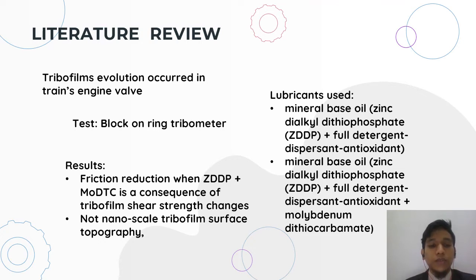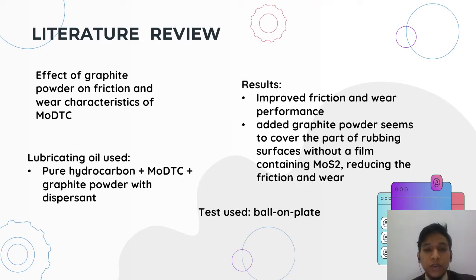topography of the tribofilm surface. The third literature review also presented a study about the graphite effect on friction and wear properties of molybdenum dithiocarbamate, MoDTC. It was found that graphite powder added with dispersant to oil consisting of MoDTC considerably improved friction and wear performance, while graphite powder appeared to be absorbed on rubbing surfaces but without a film consisting of MoS2, therefore decreasing friction and wear by preventing direct contact between the rubbing surfaces.